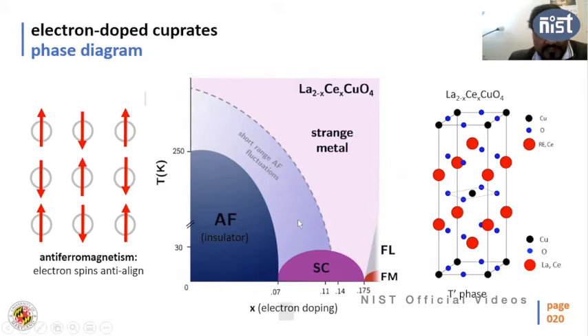There is another regime, this light blue regime, which we call the short-range antiferromagnetic regime or fluctuations. Basically, you can say some sort of weak antiferromagnet. And this dome is the superconducting dome. With increasing doping, the superconducting transition temperature peaks around 11% doping, then it comes down and goes away around 17.5% doping of cerium. Then it becomes a normal metal. We call it a Fermi liquid, which I'll discuss later. And recently I found it's not only a normal metal, it's also an itinerant ferromagnet.